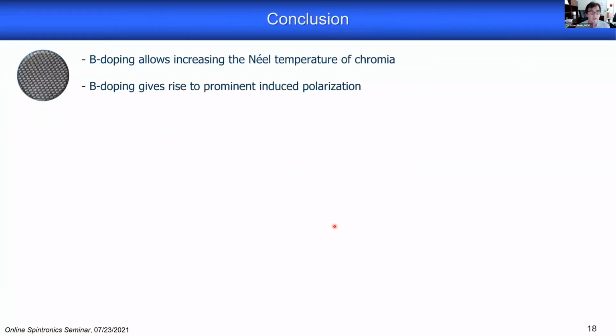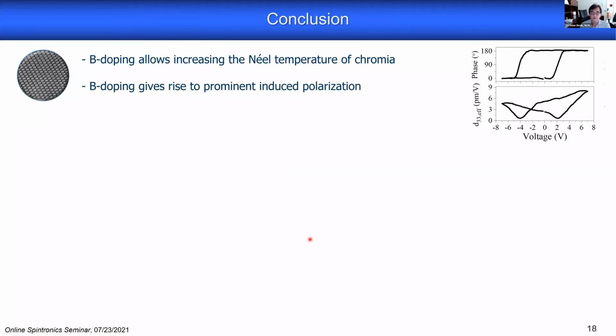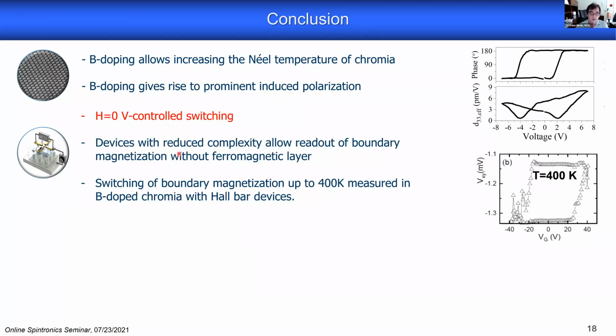So what I've shown you is that boron doping does a couple of things. As initially proposed and expected, it increases the Néel temperature as we wish. Unexpectedly, it gives rise to induced polarization, quite a significant effect. And because of this effect, we were able to create these complexity-reduced devices where we can show rotation of the antiferromagnetic order parameter by 90 degrees in zero magnetic field. That's the important point here.